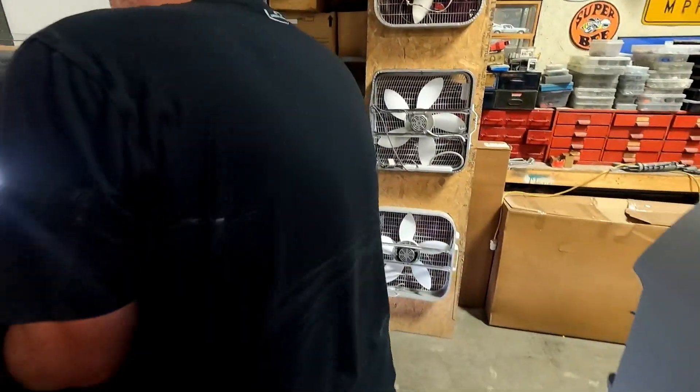We're going to show you some sandblasting here — this is just some residue on there. You blast and get all that gunk off. There's some old powder coating or something on there; we probably won't get it all off but it gets it smooth. You can see how it turns white — that's taking all the rust off. Get it as clean as possible, wipe it down, and she'll be good for powder. Powder can go over rust but you can see the texture underneath.